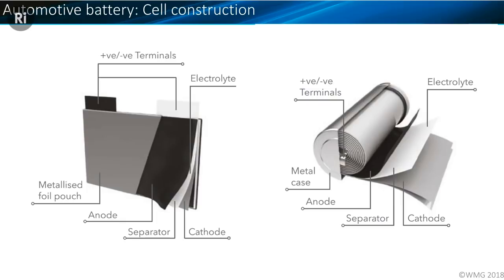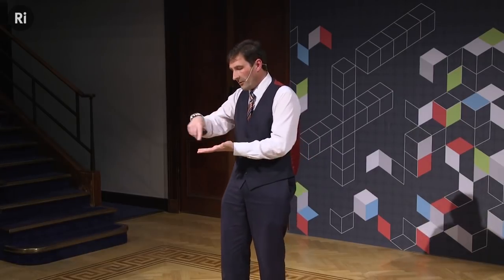And we can assemble those cells in one of two typical formats. We can cut those cells into big sheets, like rectangular sheets, typically about the size of maybe an A5 or an A4 book, and we stack them like a lasagna. And what we're doing is trying to get as much contact area as possible between the anode and cathode sheets with those separator layers in between. And if I cut them as rectangles and stack them lasagna style, I get something that I call a pouch cell. The other way that we can do this is we can print it onto very long, thin strips, and we can roll those strips together. And that makes me a cylindrical cell of the 21700 sort that you saw in Simon's presentation.